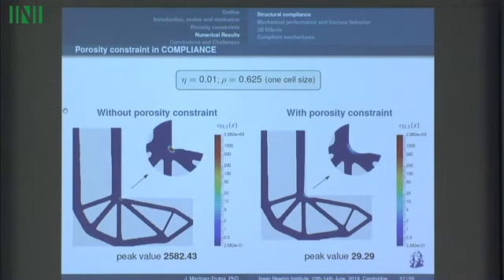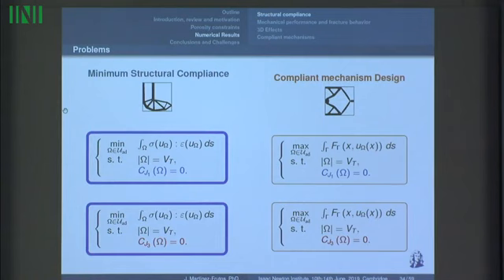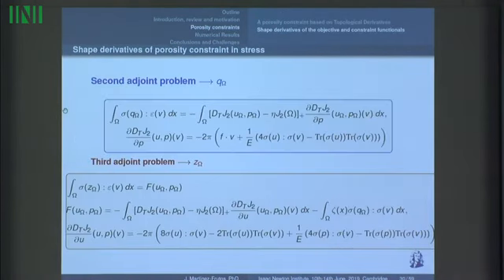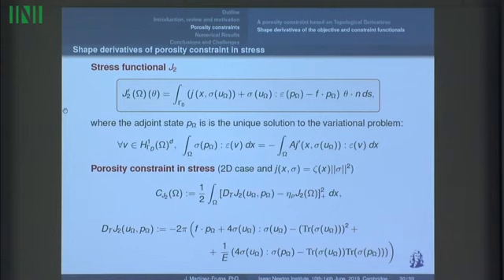Well, these are the two designs that we obtained. On the left-hand side, we have the design that we obtained without the porosity constraint, and on the right-hand side, we have the design that we obtained introducing this porosity constraint. So the effect is that the reentrant corner is smooth and rounded in this case, and the peak value of this field here is reduced a great deal. This field here is the integrand of the porosity constraint, this quantity.